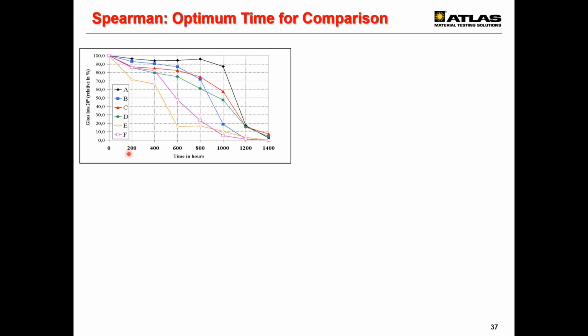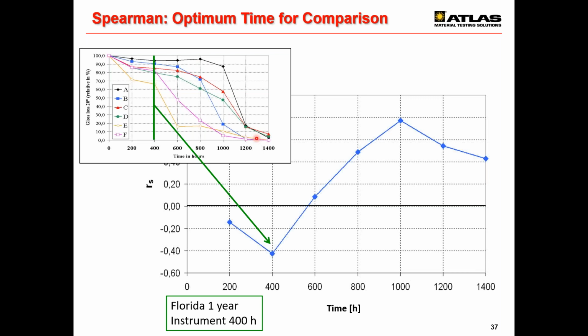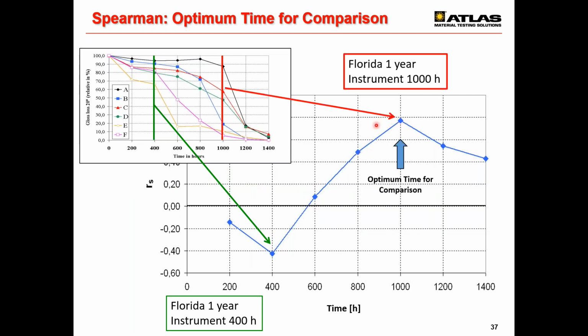However, you have other data sets, you have 600 hours, 800 hours, and you see the ranking is changing. So you can do the same calculation for each of those exposures, just assign the ranking and do the calculation of the Spearman correlation coefficient. And then you see after 1,000 hours in the instrument, you get a Spearman rank correlation coefficient of 0.8. You don't see it, but it's around 0.8.